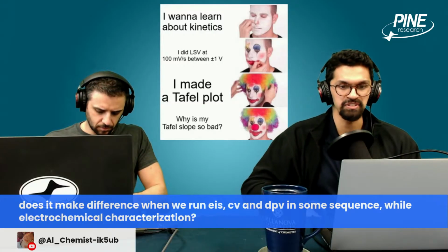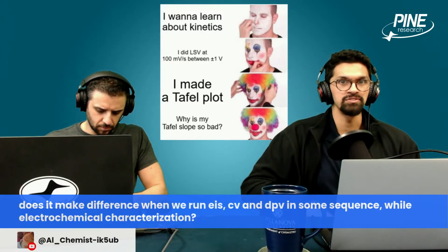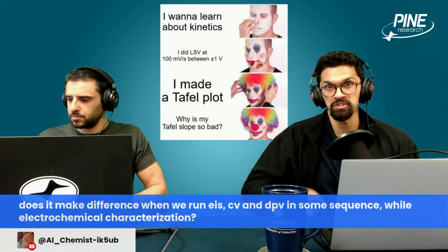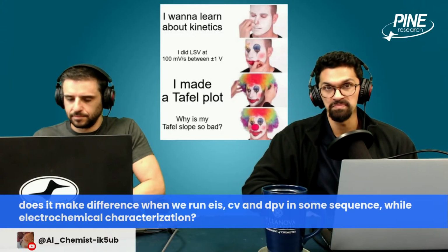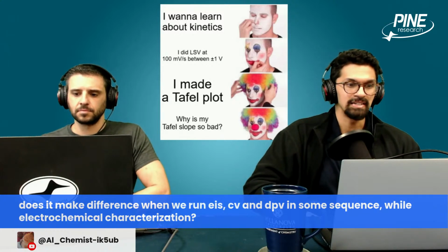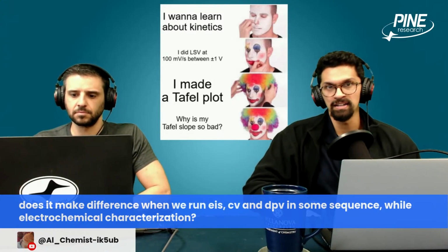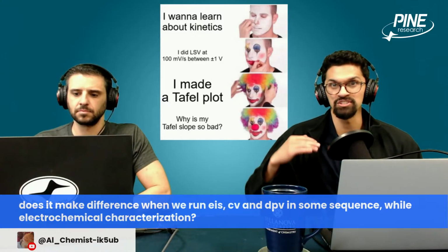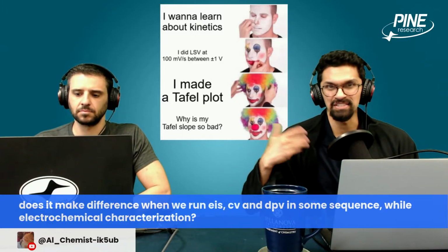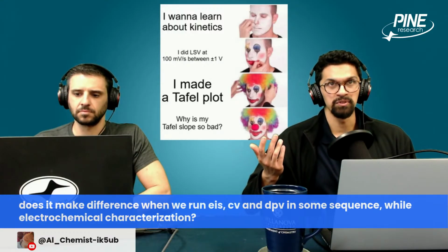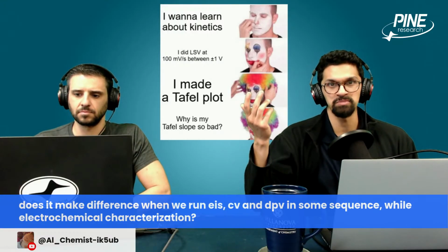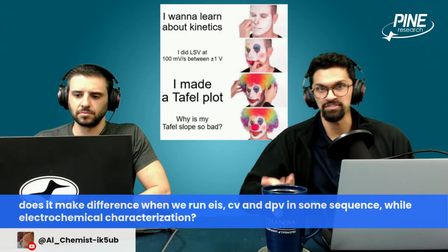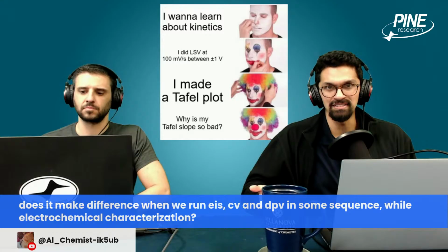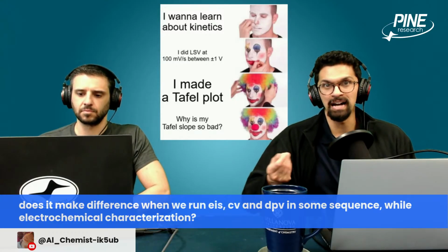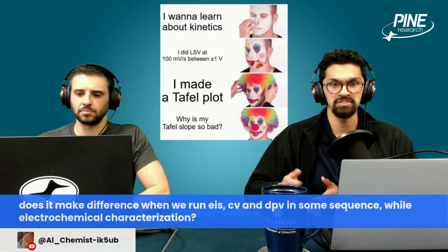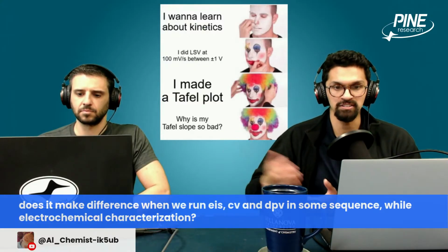Generally speaking, I'll say for EIS, EIS usually does a very small perturbation to the electrochemical system. So oftentimes it doesn't matter when you do EIS. You could do EIS before or after. It doesn't change the system where you would get different results for, say, your cyclic voltammetry. If you did a CV experiment before doing EIS and after EIS, you'd probably get the same CV data no matter what, because EIS doesn't perturb the electrochemical system enough to create some kind of problem.